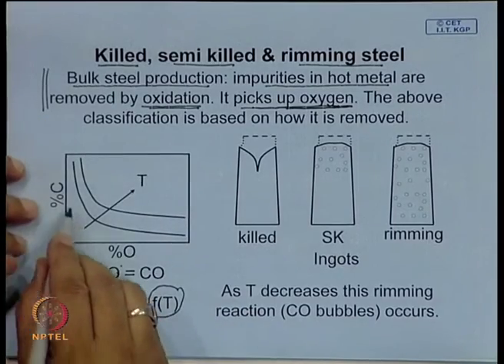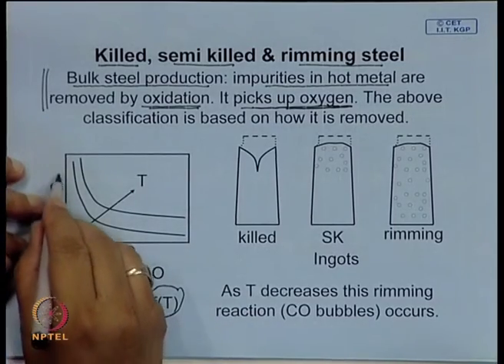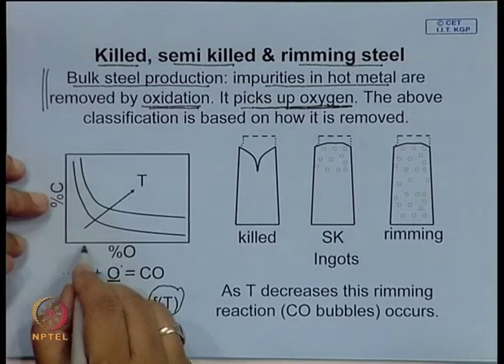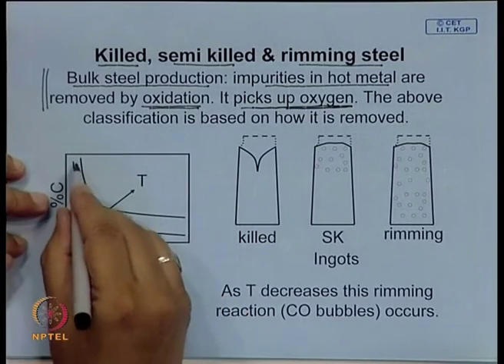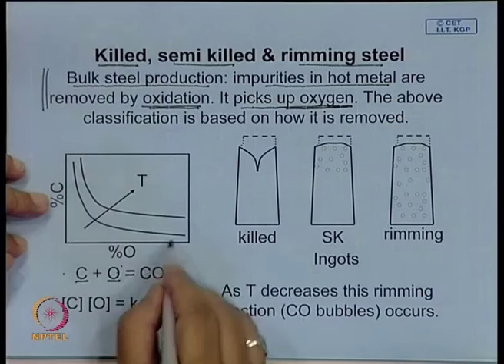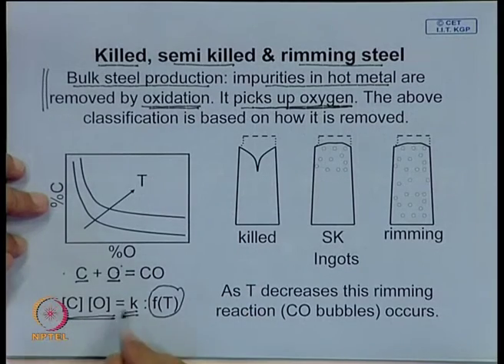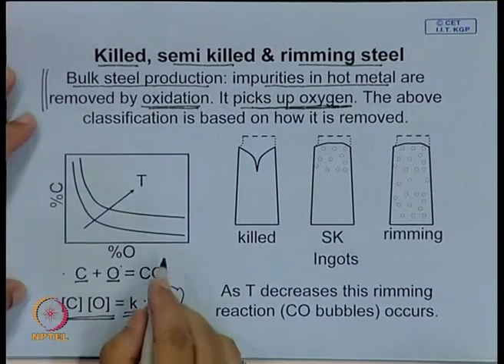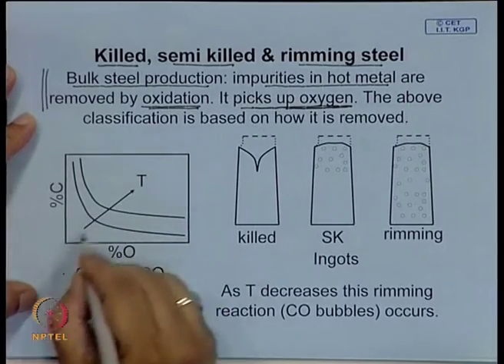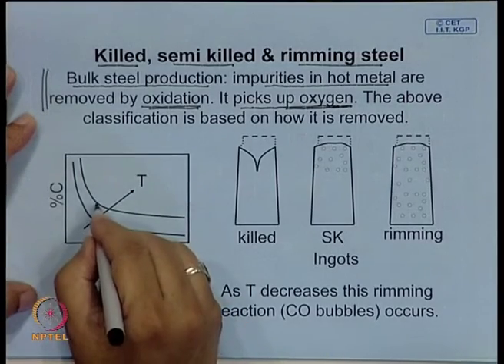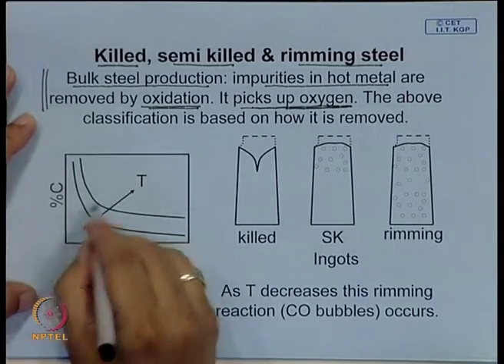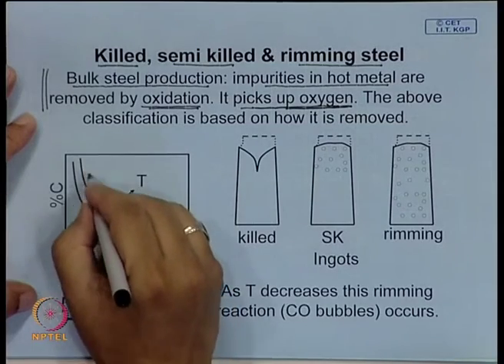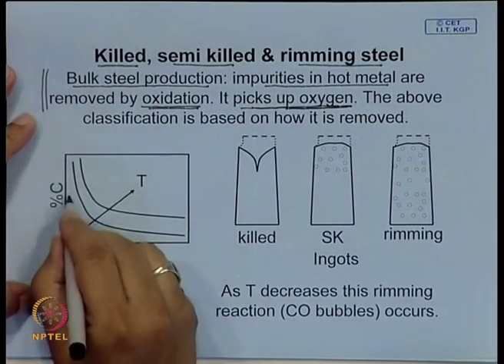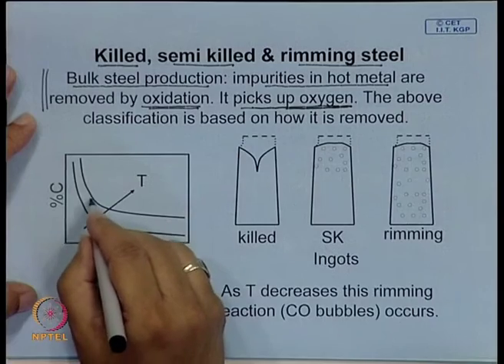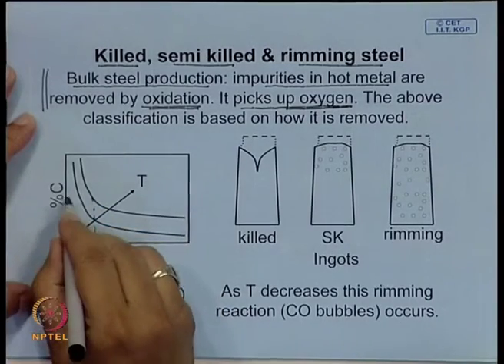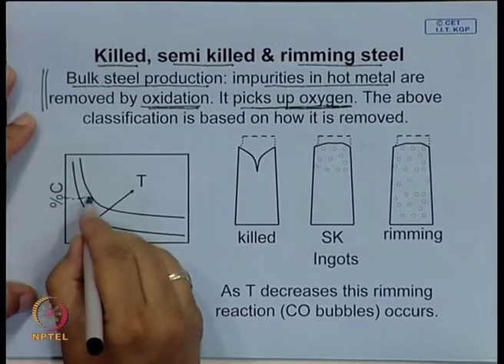And this product is a function of temperature; at a given temperature it is constant. Therefore, if you plot a graph of percentage soluble carbon in iron and soluble oxygen in iron, you will get this kind of a hyperbola, because this equation is that of a hyperbola. Higher the temperature, higher is the solubility product. So, as the temperature increases, if it has this much amount of oxygen, it will have this much amount of carbon.